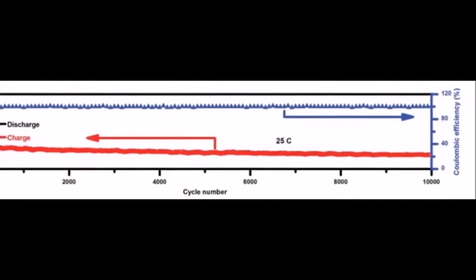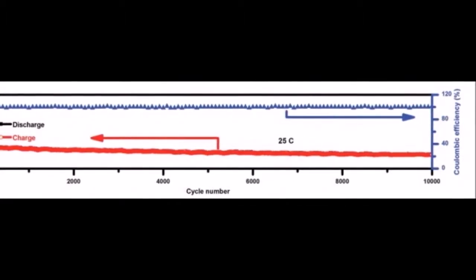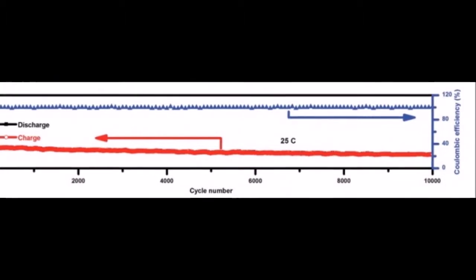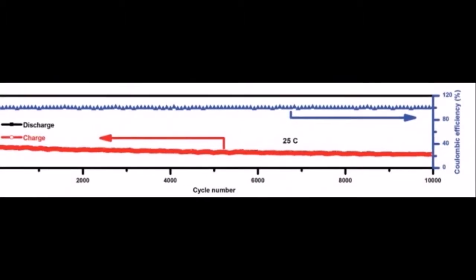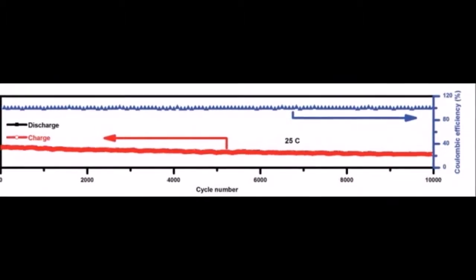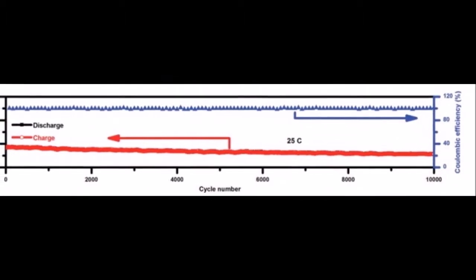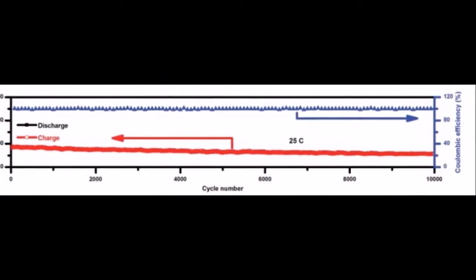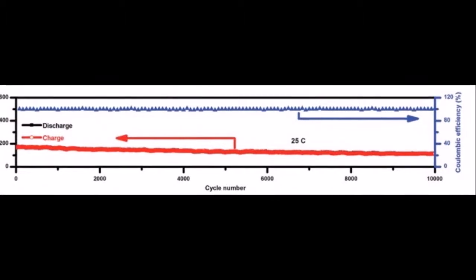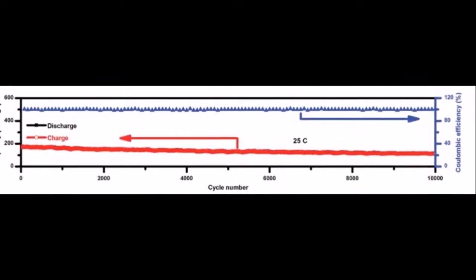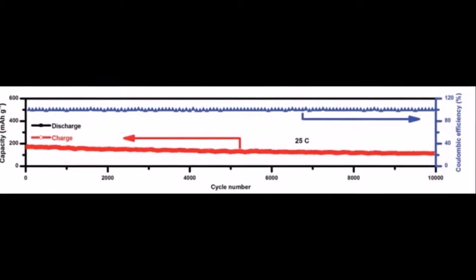Xiaodong and colleagues were able to produce titanium dioxide nanotubes which were up to 40 micrometers in size, 2 orders of magnitude longer than previously achieved, by a simple process of mixing it with sodium hydroxide and stirring. Crucially, this made the nanostructures long enough to be useful for building a battery anode.